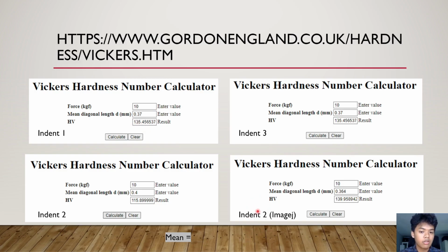And then here I calculated indentation number 2 again, but now with the data I got from ImageJ. And the result I got was 139.958942. More reasonable, it's more likely to happen instead of 115. So maybe there was a mistake in our measurement during the practical examination.